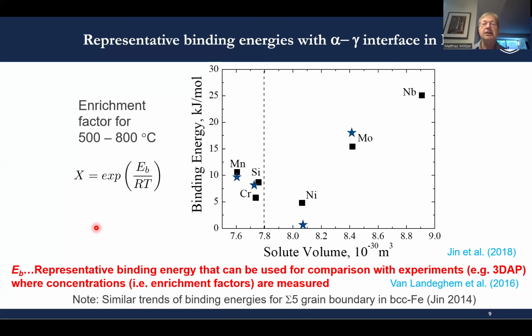And what we did see is that the experimental binding energies compare very well with the DFT computed binding energies. The alloy trends are reasonably represented, and even the absolute numbers are very similar. And that's a very encouraging result. I should also say that we would see very similar trends in the binding energies when we just consider a sigma 5 grain boundary in BCC iron, which is a much simpler simulation because we don't have to worry about this approximation for the paramagnetic state.